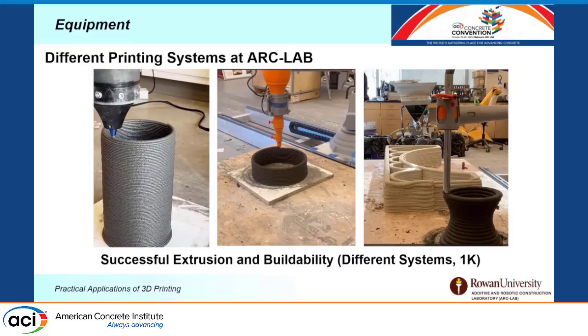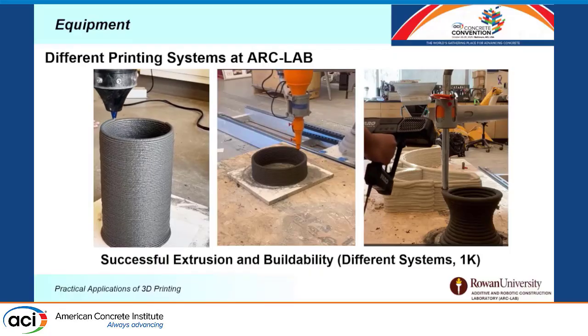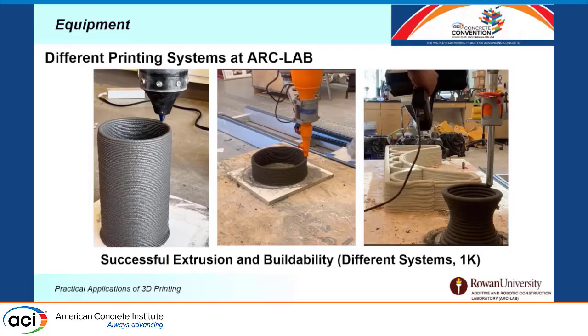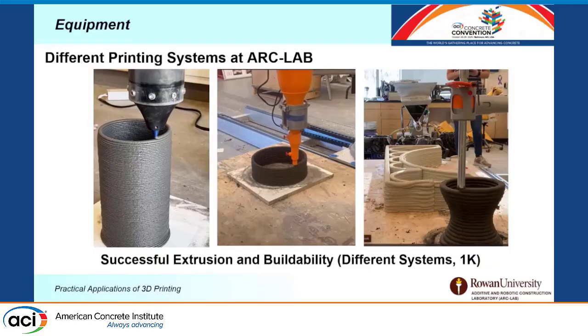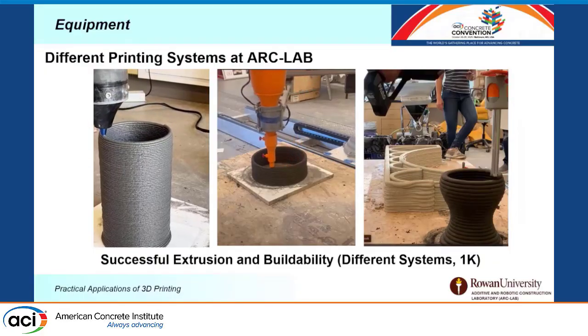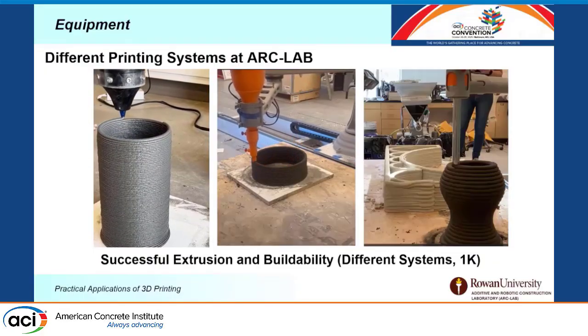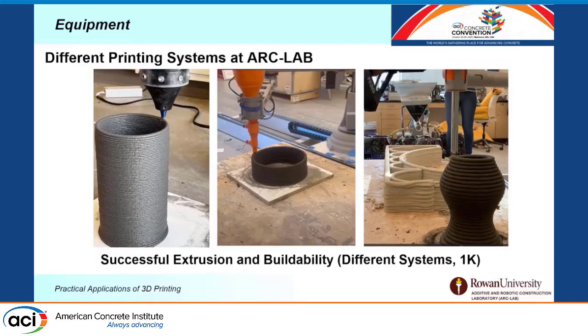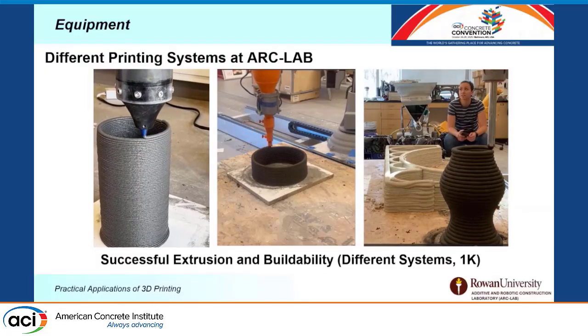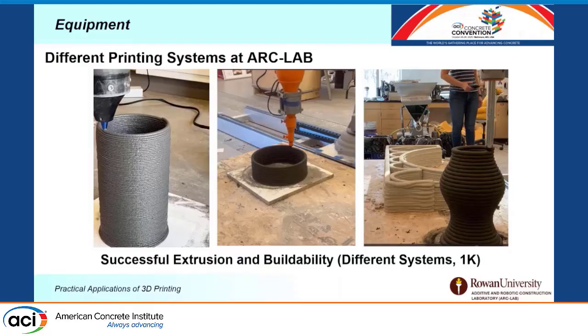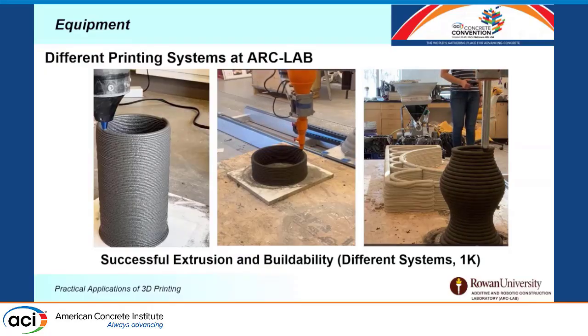But as you can see here, on the left side we are printing with a 5 millimeter nozzle, to a half-inch nozzle, to a 1-inch nozzle. And we are not using accelerator in like 95% of our mixes. We are actually achieving the slopes without any accelerant, either in the mix or at the nozzle level.